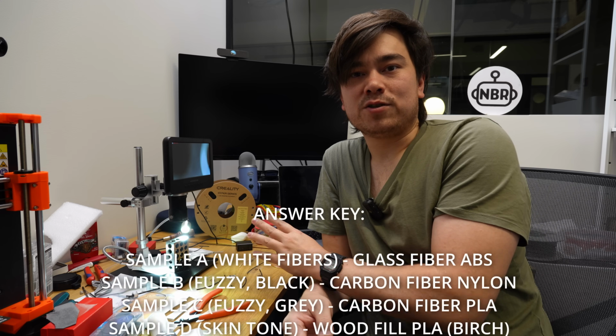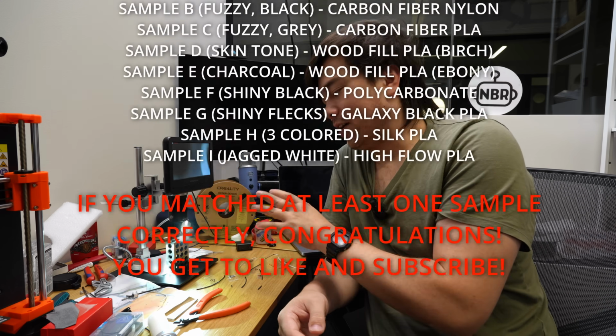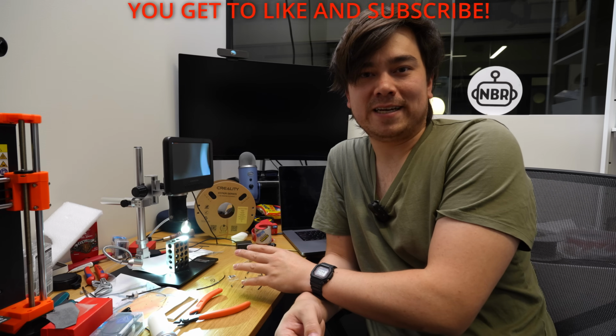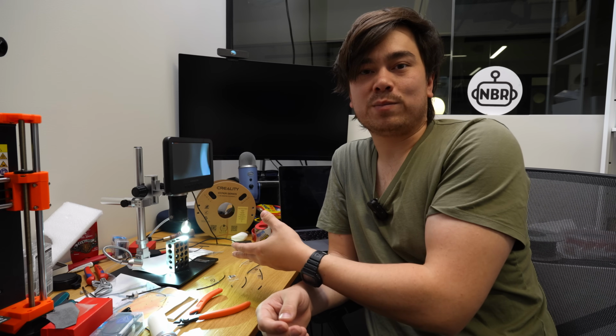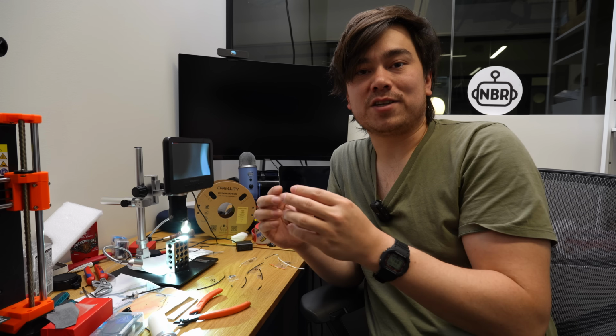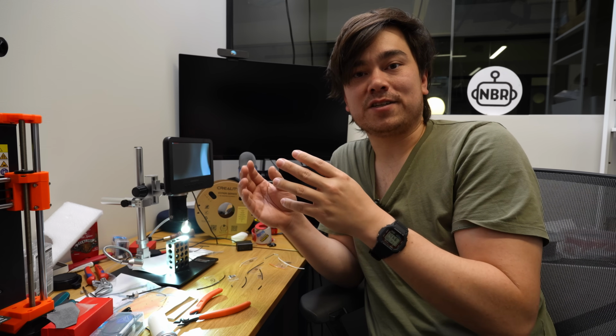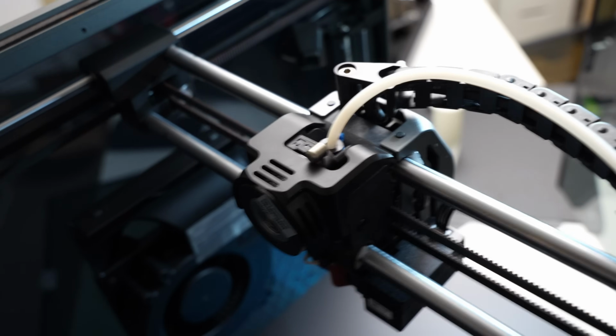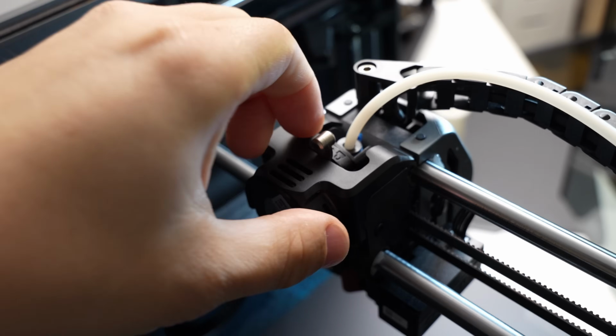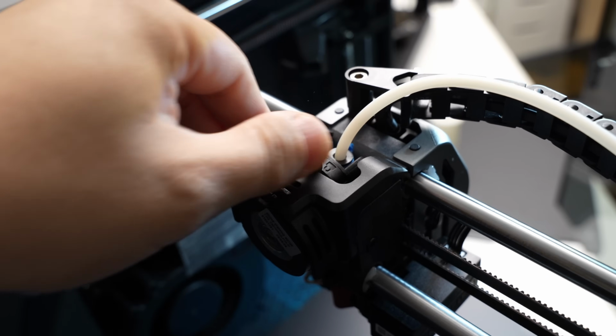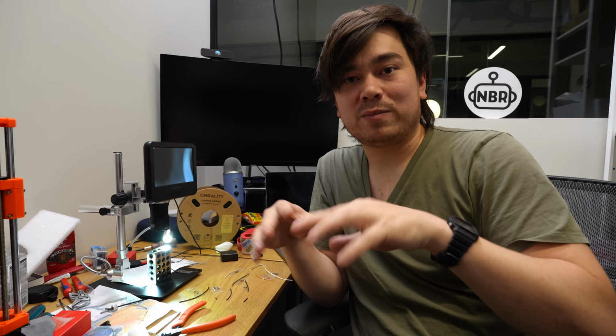So I think one of the conclusions we can draw here is that not all fiber-reinforced plastics are created equal. Depending on their processing parameters, more or less of those fibers are going to be available at the surface of the filament. Now, it's not just a matter of handling these materials, it's also printing them. So when you're running your printers, you've got extruder gears biting into the sidewalls of that filament. Those gears are going to pull some of those fibers off and they'll get loose and go all over the place.